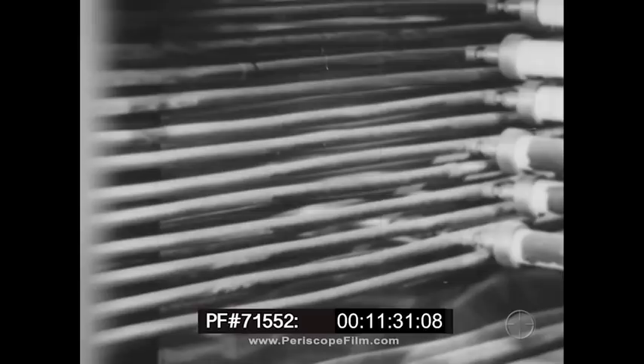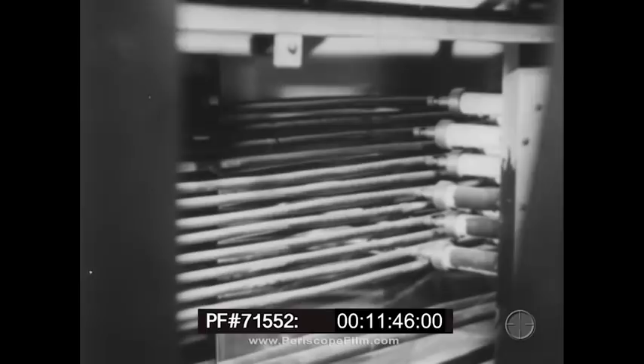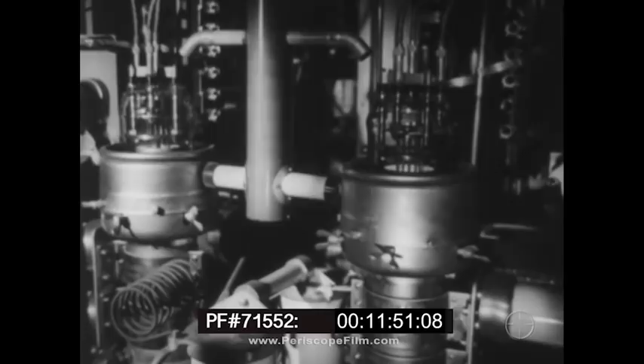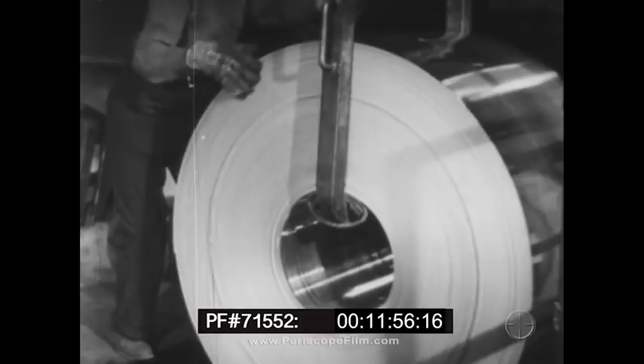Note the horizontal bars in this close-up. These are parts of one of the high-frequency coils that affect the tin flow. If you look closely, you can see the difference in texture between the porous tin entering the top of the coil and the shiny flowed tin leaving at its base. And these are the tubes that generate the high-frequency current which makes the entire process possible. Another important result of this new Westinghouse electronic process is time-saving. Tin can now be flowed at a rate of more than 1,000 feet a minute.